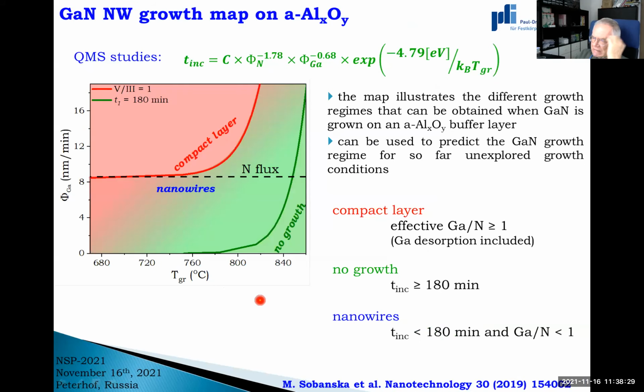Having this knowledge, we can ask a question: if we take this substrate with aluminum oxide, what is the range of growth parameters under which we create a compact layer, we create nanowires, or there's no growth at all? To answer this question, we create this kind of growth map in which we have gallium flux and growth temperature, while nitrogen flux is fixed in this case. And using this formula, we try to fill this map with some boundaries.